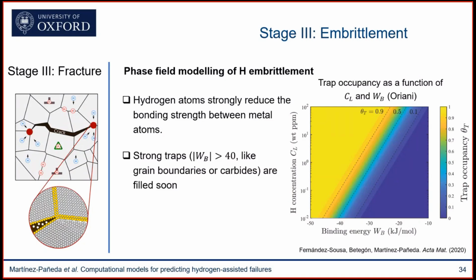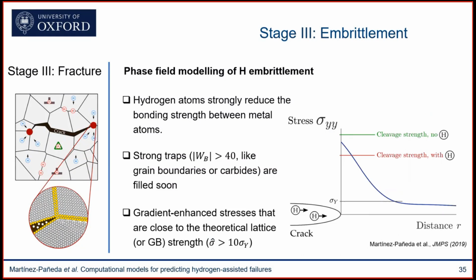So then the question that is missing is, okay, is this 20 to 30 to 40% reduction in bonding strength sufficient to trigger a change from ductile fracture to cleavage fracture? And we know that the theoretical lattice strength of the grain boundary is 9 to 10 times the yield stress. So a 30 to 40% reduction maybe is not enough. But when you account for those GNDs, for those plastic strain gradients that I mentioned before, you have these macroscale stresses that are sufficiently high. They're not high enough in the absence of hydrogen to reach the cleavage strength. But the moment you bring hydrogen into the picture, you get this 30 to 40% reduction in cleavage strength, and then these two lines cross, and you have a story. You have a model that is naturally capable of predicting the change from ductile fracture scenarios to brittle fracture scenarios just by introducing hydrogen to the model, without any fitting parameters whatsoever, just an atomistic calculation that you need to run once in your lifetime offline.